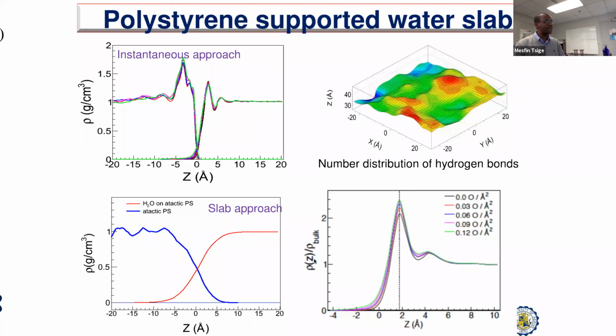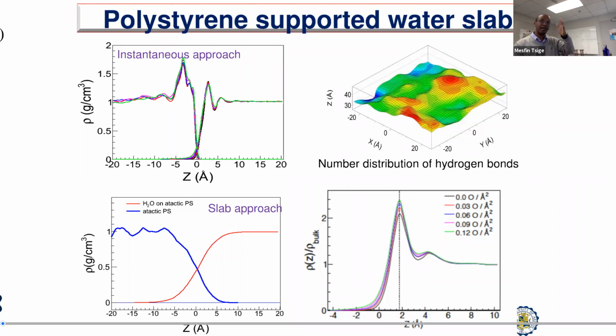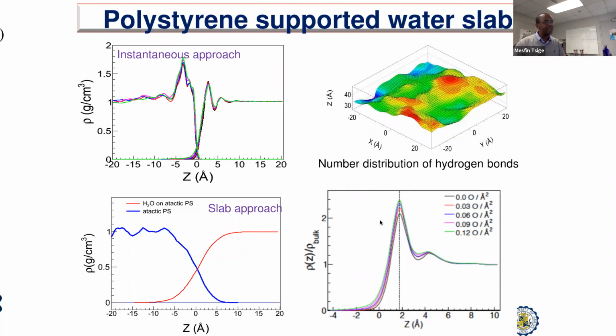So we have looked at the density of water close to our polystyrene surface, as a function of distance from the surface. 0 refers to the instantaneous surface I told you about. Every point has a 0 reference. What we see is a high density close to the surface. For historical reasons, I have to say that there was a debate 8-10 years ago about the depletion region of water near hydrophobic surfaces. I think some researchers said there could be about 5 angstrom or a nanometer depletion region when we bring water in contact with hydrophobic surfaces. But others who used spectroscopy approaches said that's not true. And after back and forth, the community said the depletion region is not really possible, even close to hydrophobic surfaces.